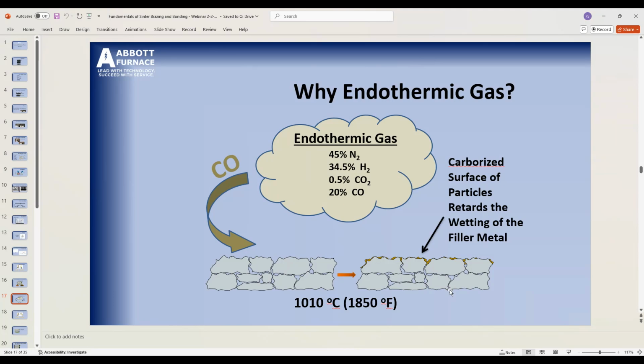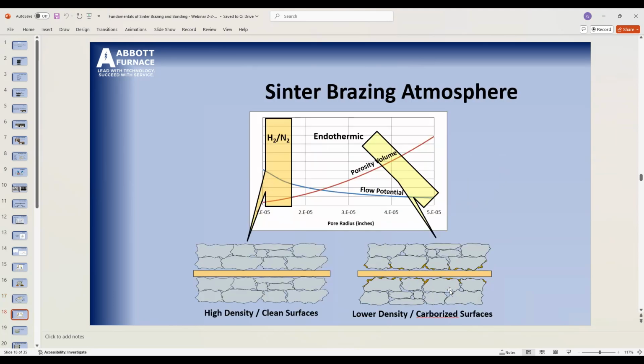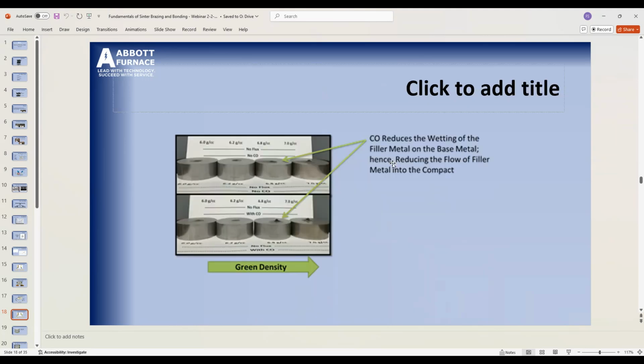And now what did we do? We just made the surface dirty. We made the pores dirty. So now if we have the right gap and we make it just a little bit dirty, what we're doing is we tip this rectangle. So now the flow potential is even lower because it doesn't want to go over the dirt, even though those pores are pretty big. So you tend not to steal as much of the filler metal from the gap. Okay. So if we look, what we basically have here is, excuse me, sorry. We have CO present.